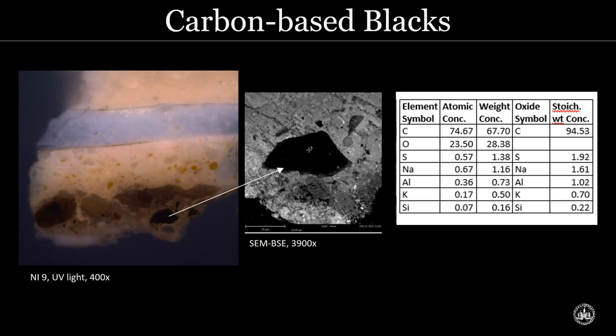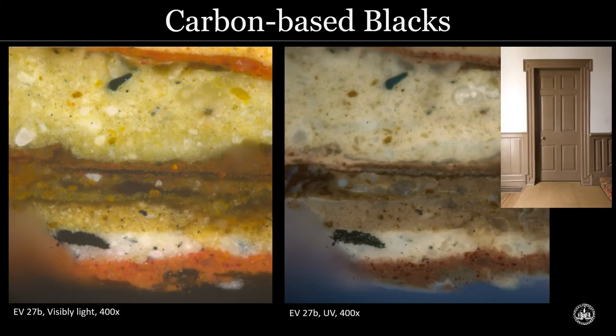So I wanted to make sure they were not manganese oxides, which are black minerals that are associated with umbers and siennas. But no, SEM EDS told us that these contained mostly carbon. There was no manganese detected, so this is certainly a carbon-based black, not a bone or an ivory black. Those would have contained calcium and phosphorus from the starting material. So its large size also tells me that this is a carbon-based black made by burning wood or other vegetable matter. It's clearly not a soot or lamp black, which would have been a much finer particle size.